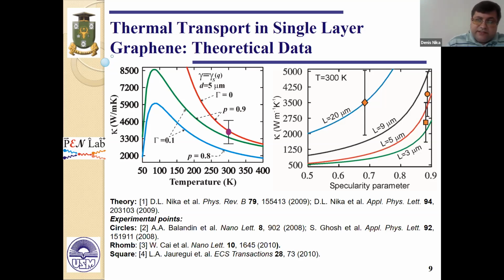We can conclude that thermal conductivity of graphene is very sensitive not only to temperature, which is typical for most materials, but also to extrinsic parameters of structures: flake lateral sizes and defects of crystal lattices. You can see that depending on these extrinsic parameters, we can change the thermal conductivity between 2,000 watt per meter Kelvin and 8,000 watt per meter Kelvin. Experimental points are depicted here by circle, rhomb, and square. These points are from different experimental groups and were obtained using different experimental techniques.